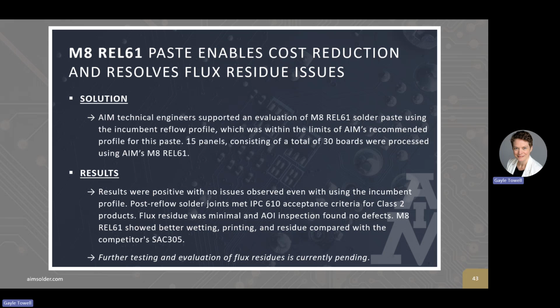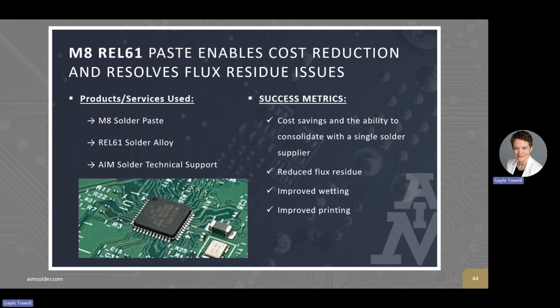There were no issues observed, even with using the incumbent reflow profile. Post-reflow solder joints met IPC 610 acceptance criteria for Class 2 products, and flux residue was minimal, and AOI inspection found no defects. So it showed better wetting, printing, and residue compared to the competitor's SAC305. Again, this is just a summary of the products and services used in this application and the success metrics. They were able to save costs, consolidate with a single supplier, reduce residue, improved wetting, and printing performance.